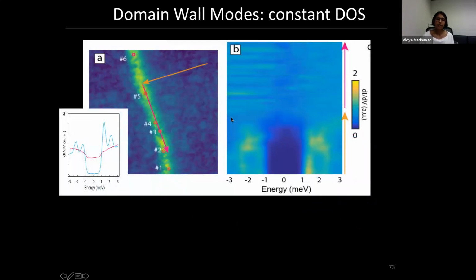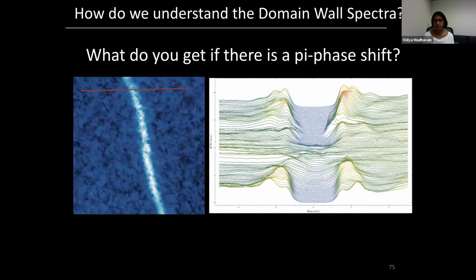So in fact, you can see this. You can take spectra along this line in pink. And if you do that, this is just a color plot. You can see that this is the superconducting gap here, with spectra along this line. It's dark, and as soon as you get to this line, you have this finite density of states inside the superconducting gap. More interestingly, the density of states is a constant, right? So you have a finite constant density of states.